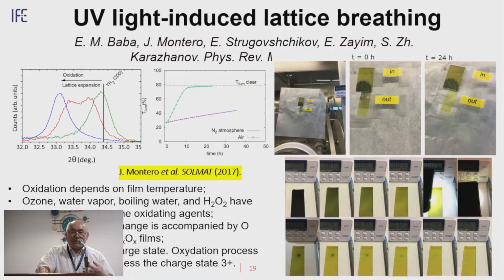So when in the next day morning we were picking up the sample, we found the sample is totally dark. Then we said, okay, probably we did something wrong. But within, again, 2-3 minutes, it got bleached. Then we found that the temperature of the sample is playing a key role. And that oxygen is coming, in fact, from the environment because our sputtering unit is not connected to the glove box. So this was another very exciting finding. Then we see the atmosphere is playing a big role.